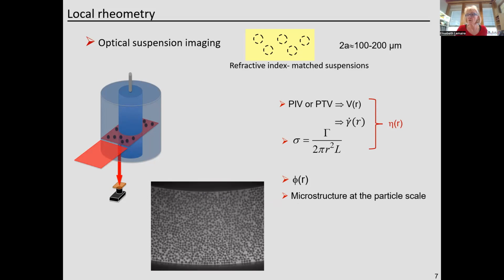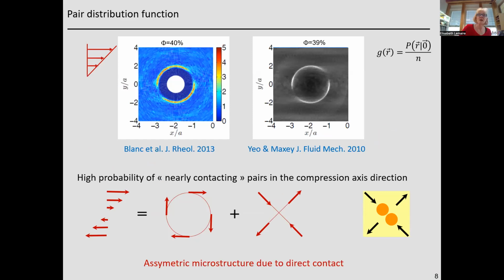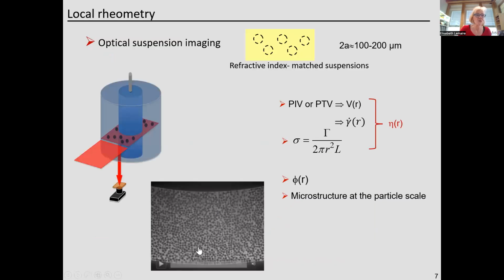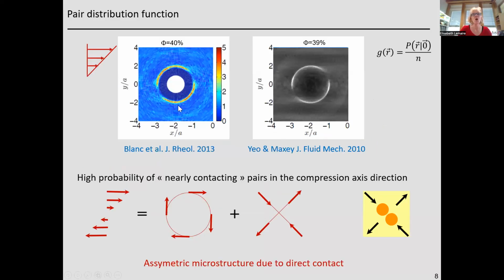The microstructure at the particle scale can be represented by the pair distribution function. The pair distribution function is mainly the probability to find a particle at a position R, knowing that there is a particle at the origin. On this kind of picture, we take one particle, this one, for instance, and we measure where all the other particles are situated relatively to the reference particle. Then we choose another reference particle, and again we measure where all the other particles are situated relative to the reference particle. With this statistical tool, we can draw a pair distribution function.